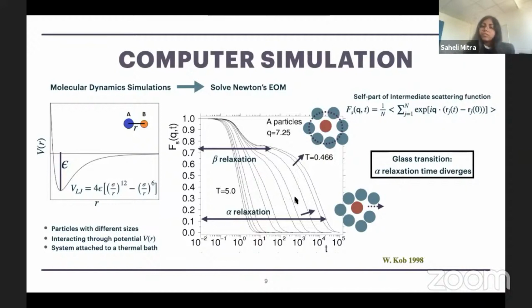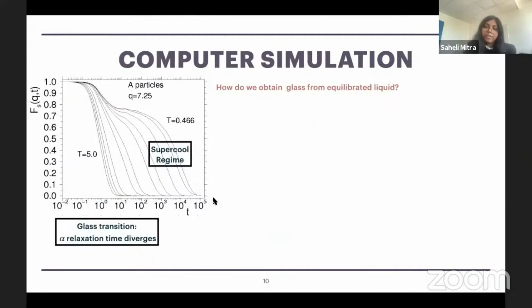Pictorially, we can think of this as in shorter time, the particle is trapped by the cage formed by its neighbors, and in long time, when all parts of the system start to move, it can escape from the cage, relaxing from its initial configuration. Now, this alpha relaxation time actually diverges at the glass transition. So from the simulations, it is not possible for us to relax a system until it reaches its glassy state. So how do we obtain a glass from an equilibrated system?